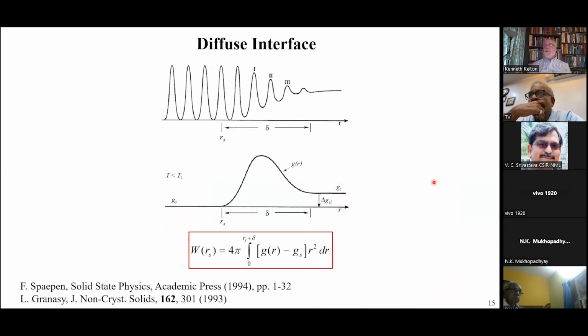Okay, well, it turns out there is a theory that can handle this. It's called the diffuse interface theory. Basically, what does it mean to have a diffuse interface? And I show it schematically here, where you have periodic arrangements of atoms, and as you get closer to the liquid where you don't have periodicity, that periodicity in the cluster starts to decay. That means then that Gibbs' idea of having a sharp dividing surface isn't correct. You can't say, here's where the surface is and here's where the volume is. Instead, you should focus on the total free energy, and the total free energy will have some profile where it will go from the free energy of the liquid to the free energy of the solid. But in the process of crossing the interface, there'll be an increase in the free energy. If we knew what this profile, what this curve was, it would be trivial to calculate the work that's required to form a cluster of a given size. But we don't know what this profile actually is.